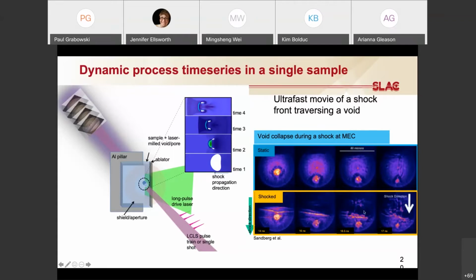Then followed by what we've affectionately referred to as the black fog, which is behind the main elastic and plastic waves here, and we think this is actually the ablation front moving through. This was done at a somewhat lower X-ray energy, I think 8 or 9 keV. So we've considered this in upcoming experiments so that we can actually see through this black fog.